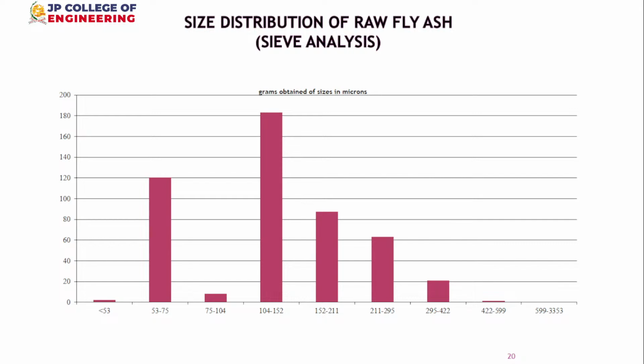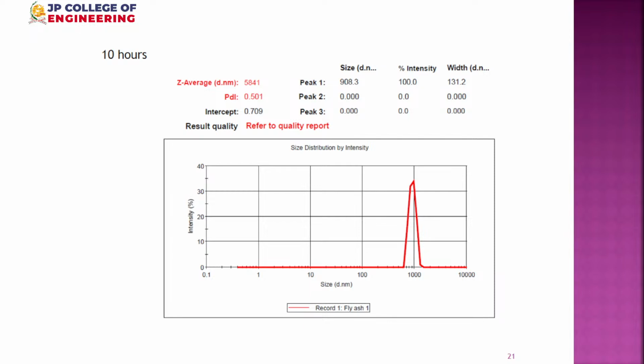We have to go for minimizing the size, so we went for ball milling. Next slide, please. On ball milling, and then analyzing in our particle analyzer, after 10 hours of ball milling we could see that we get around 900 nanometer. This is 1000 nanometer means almost 1 micron. So we get around 0.9 micron on 10 hours milling.